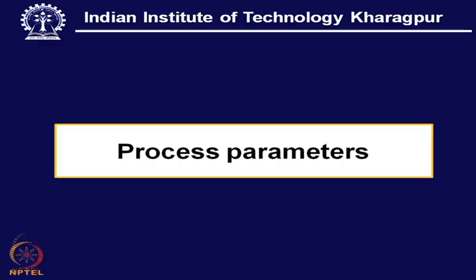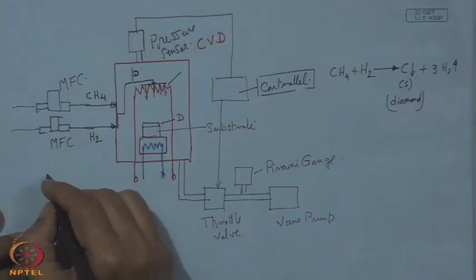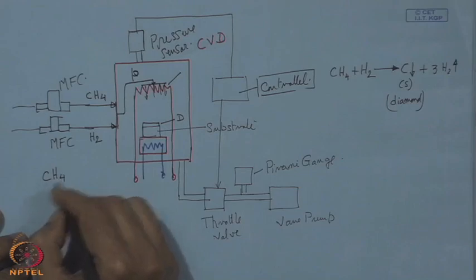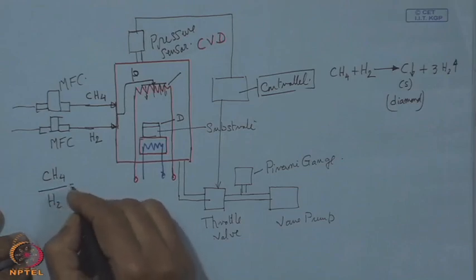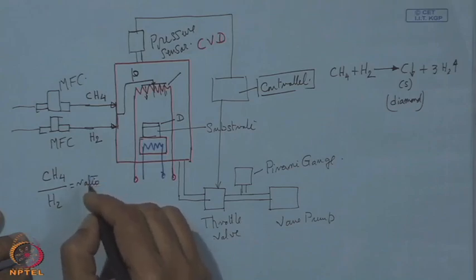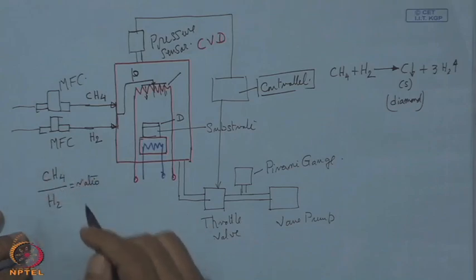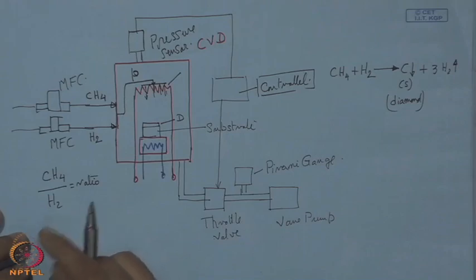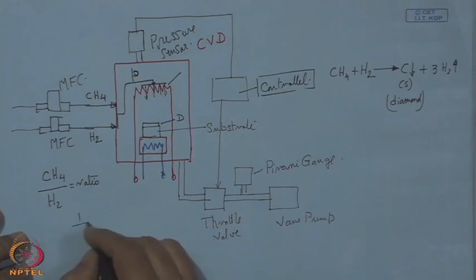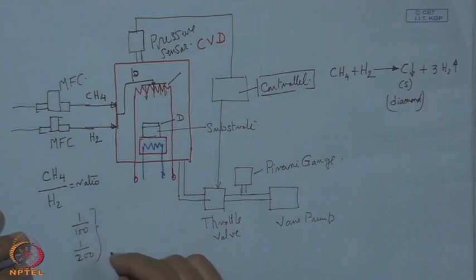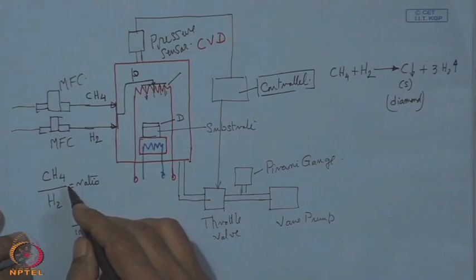Now, process parameters. The most important process parameter is the CH4 by H2 ratio. We mean the flow ratio. All review of research suggests that it is mostly kept between 1:100 to 1:200. It depends upon certain other requirements, but this is the range of work. That means, if it is 100 SCCM, it is 1, or it can be even 0.5.